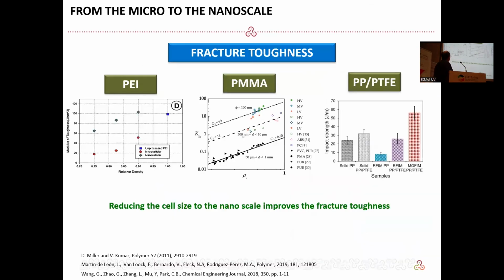extensively, I would say. I will focus on this because these are from the literature, other research from some colleagues in different countries. But here you see the toughness, so the energy you need to break a sample, basically. These are the microcellular materials. Cell size is 50 microns to 1 millimeter as a function of relative density. These are microcellular. Cell size is below 10 microns to 500 nanometers. And then you have materials with less than 100 nanometers. You have a clear improvement of the mechanical performance.